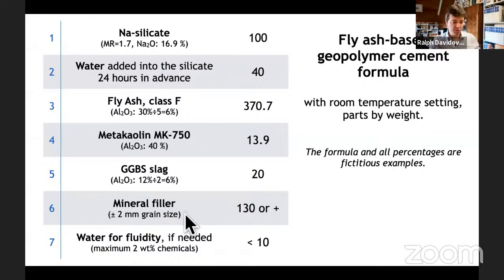Then we add mineral fillers and water for fluidity. So these are 100 grams of silicate, 40 grams of water, 370 grams of fly ash, 13.9 grams of metakaolin, 20 grams of slag, whatever mineral filler you need to add, and if you need some fluidity, 10 or below. So you have a very specific formula that follows the chemistry.